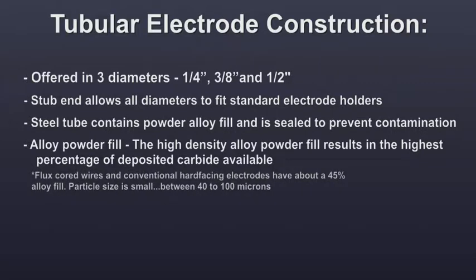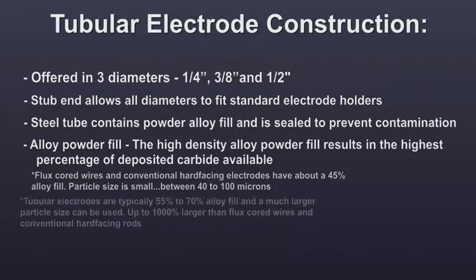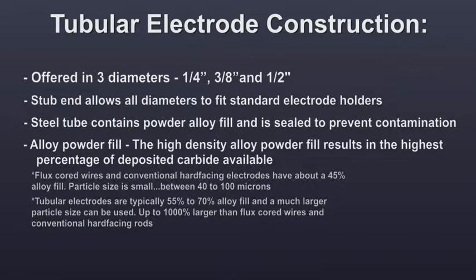Flux-cored wires and conventional hard-facing electrodes have about a 45% alloy fill. Particle size is small, between 40 to 100 microns. Tubular electrodes are typically 55% to 70% alloy fill, and a much larger particle size can be used. They are up to 1,000% larger than flux-cored wires and conventional hard-facing rods.